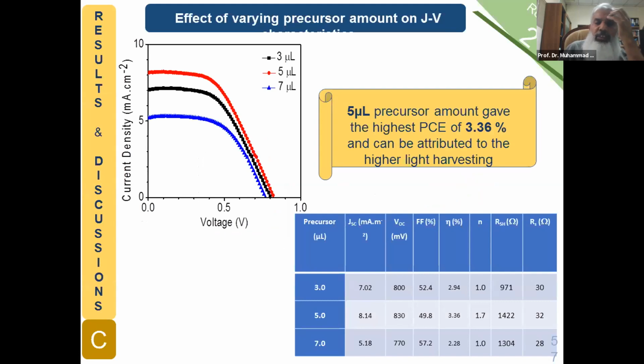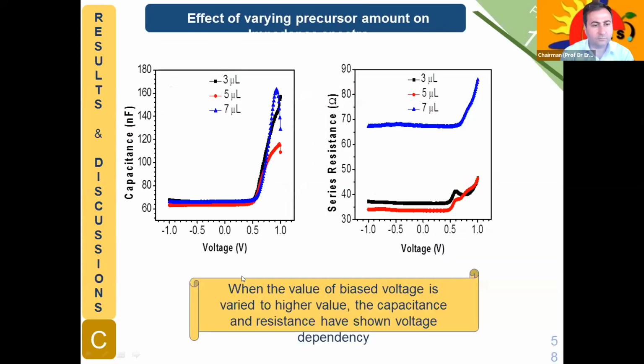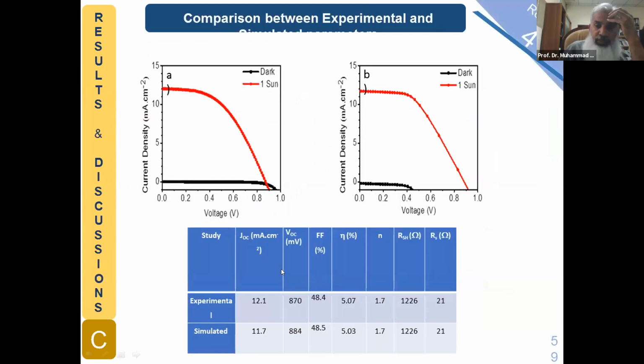There was another study carried out using different precursor concentrations. So we were able to find highest performance corresponding to precursor amount of 5 microliter. And that's the impedance spectra we carried out.